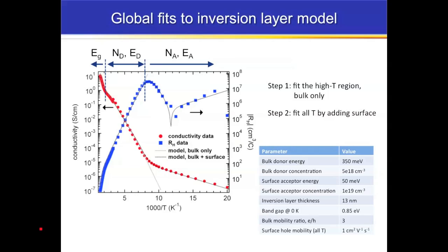And so you can understand that at high temperature the conductivity and the properties of the material are governed by the band gap. At intermediate temperatures you're dominated by this donor, and at low temperatures you freeze out the donor and the surface is basically dominating the behavior of your material.